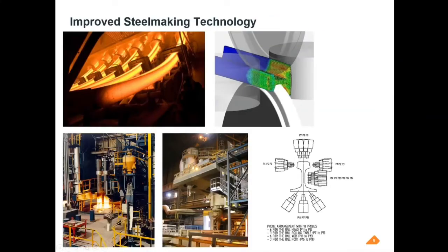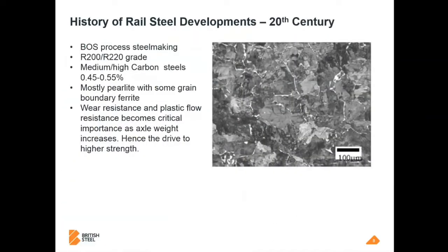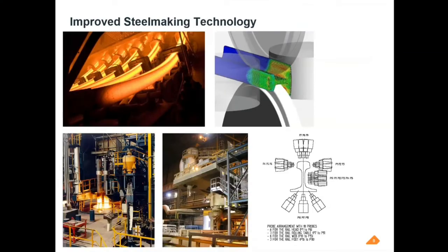Not only have we increased the strength of the alloying and the carbon levels and improved the material properties, the technology has also improved. So at the top left there, we introduced continuous casting. In the UK, it became mandatory for all rail steels in 1976 to be manufactured from continuous cast blooms. And it was a quantum leap forward in rail safety.